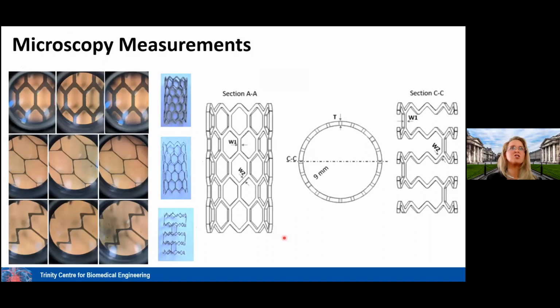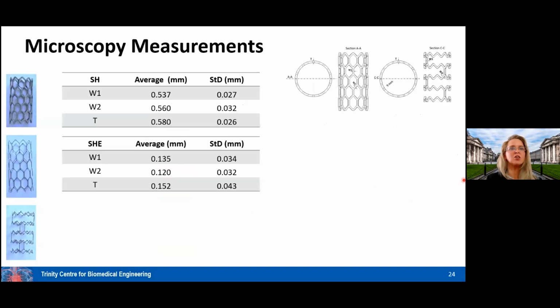So you can see here different microscopic measurements. This one is actually thinner. As I said, given the time to thin out the struts, you can see we got thinner struts here than we did with the novel etched design, where we just removed the support struts. And you can see that they are quite uniformly etched. So we could get this novel design and we could reduce the thickness. Let's look at some of the thicknesses here.